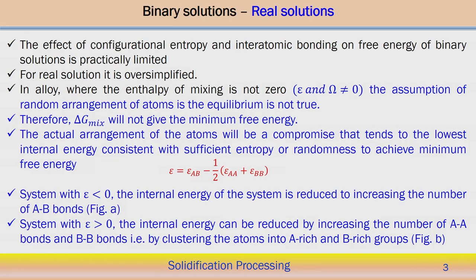In case of the ideal solution, we normally started with the configuration entropy and we neglected the enthalpy of mixing. But in the regular solution, we consider the inter-atomic bonding on the free energy of the binary solution and discuss the regular solution — the estimation of the free energy change associated with the regular solution. But configuration entropy and inter-atomic bonding or free energy of the binary solution is basically practically limited.